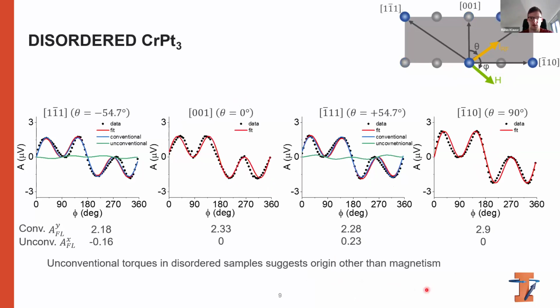And we further confirm this by measuring the disordered sample that's paramagnetic, so there is no magnetic ordering, and we see exactly the same results as for the ordered sample, which again suggests that magnetism is not involved in generating these unconventional torques.